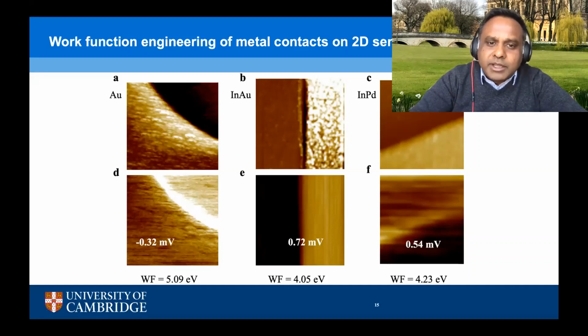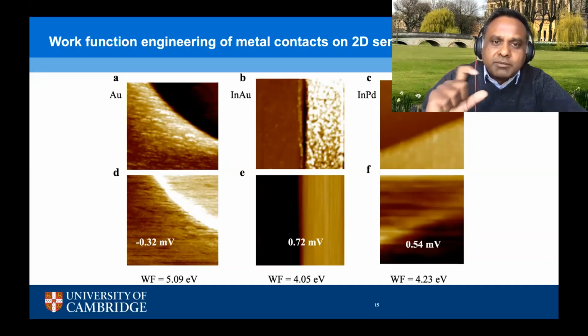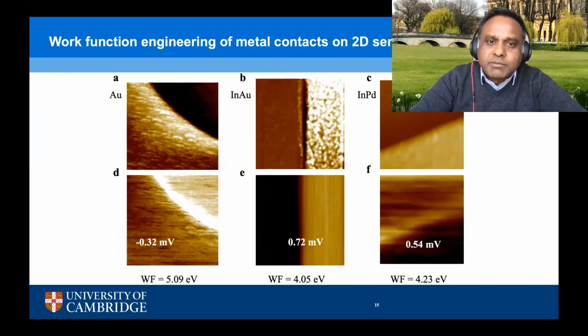And in our TEM analysis, what we found is that after annealing at 200 degrees C, where we get the best device characteristics, the indium and gold have completely intermixed, but the interface is still preserved. The van der Waals interface is still preserved. And so this intermixing gave us the idea: what if we deposit the indium first and then say a high work function metal like palladium on top, and then cause intermixing with the work function increase.